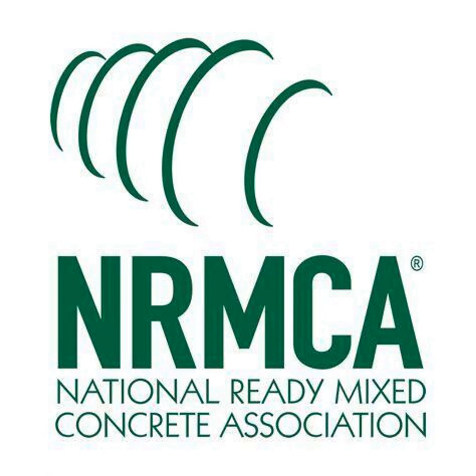Well, we have a published what we call a technology and practice sheet. We got CIPs, which you might be familiar with. They are one pagers on various topics, but we also got a TIP, technology and practice series. And one of the topics that we recently released was steps that you can take to reduce your carbon footprint. So we say, okay, you can use a high range and reduce your cement content that way, optimize your mix, or you could use increased amount of SCMs. You could use a type 1L cement.